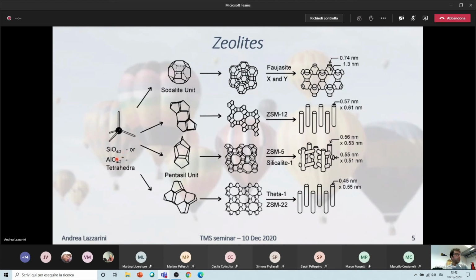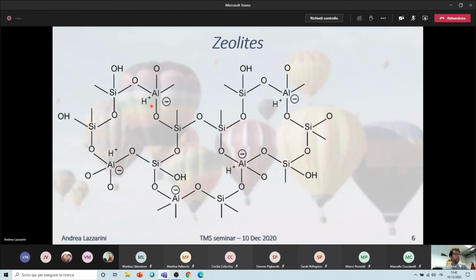Zeolites, having the introduction of aluminum oxygen tetrahedra inside the structure, naturally present acidity, because aluminum has a lower positive charge than silicon. Therefore, being surrounded by all oxygen atoms, it carries a negative relative charge that is usually counterbalanced by protons. These protons make the activity of zeolites, because they are used as acid catalysts.